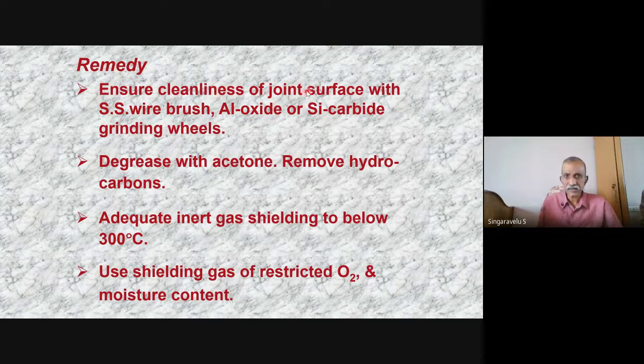The titanium surface has to be cleaned with a stainless steel wire brush. Don't use this wire brush for other applications. An exclusively separate wire brush has to be kept, and that should be made of stainless steel. It is very much important. Aluminum oxide or silicon carbide grinding can be used. Degrease with acetone, including the filler rod and the areas.